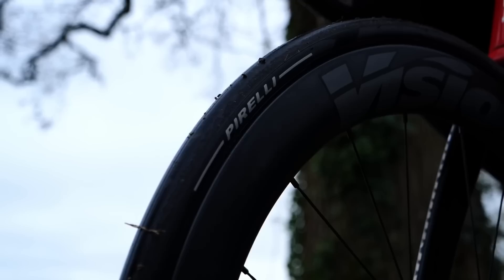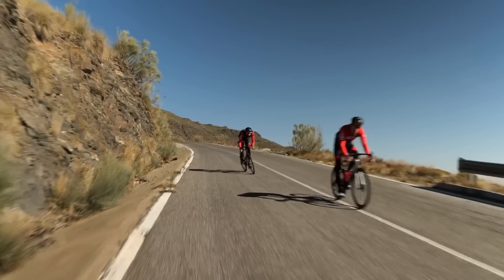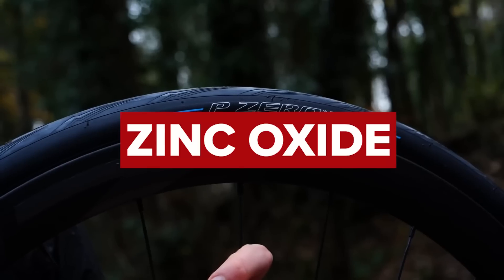That was the original vulcanization process. As technology has developed, manufacturers have started including many more additives as well as sulfur into their tire compounds to better tweak and manipulate the material properties. A lot of them are closely guarded industrial secrets, but some are known about — some brands even claim to put graphene into their tire compounds. Well-established additives include carbon black, which protects the tire from UV damage and gives it its black color. Silica is often added to make tires quieter and reduce rolling resistance. Other compounds such as zinc oxide are added to accelerate the vulcanization. The more complex a tire compound is to produce and the more ingredients it has, the more expensive it's going to be.